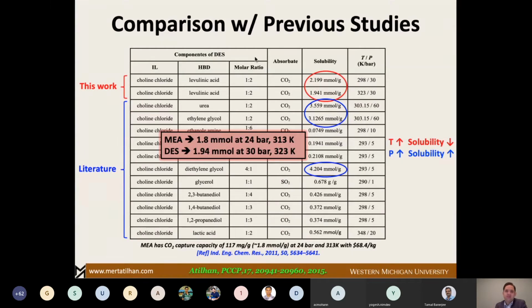So we wanted to compare our results with the common state of the art. There is no direct comparison. We could have measured monoethanolamine or MEA in our system, but we didn't because of time restrictions. We just picked one of the published data. So they are not directly comparable, but we are still in the ballpark. Which means that the choline chloride levulinic acid that we selected, 1:2 ratio, was pretty much giving us a similar result in terms of CO2 solubility.